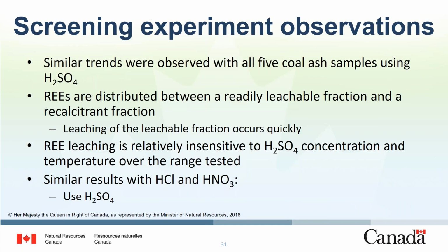So in terms of some significant observations from the screening experiments, similar trends were observed with all 5 coal ash samples using sulfuric acid. The REEs are distributed between a readily leachable fraction and a very recalcitrant fraction, and the leaching of that leachable fraction occurs very rapidly. The RE leaching is relatively insensitive to sulfuric acid concentration and temperature.